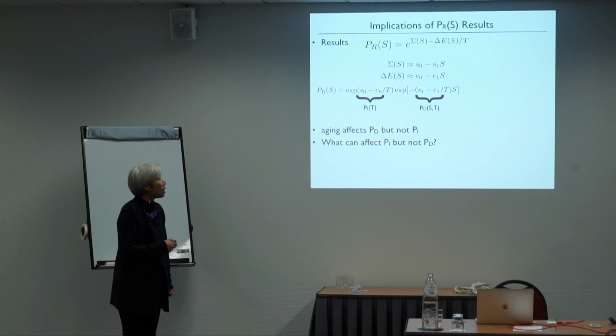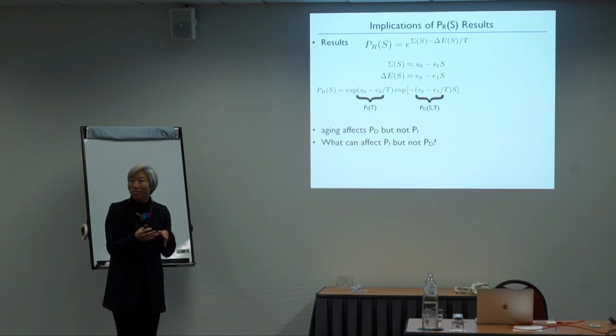So we thought, well, what is this piece? Where does it come from? One thing that would not depend on age, I can think of there being two contributions to the energy barrier. There's this contribution that depends on softness, but then there's this contribution that doesn't depend on the softness. Where does it come from? So we thought, well, maybe there's a simple physical picture that says if a particle rearranges, it gives rise to some strain that propagates outwards.